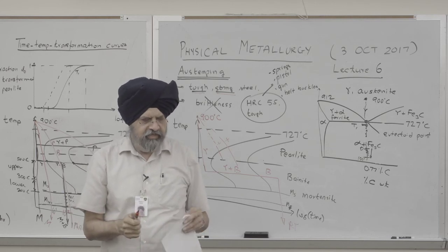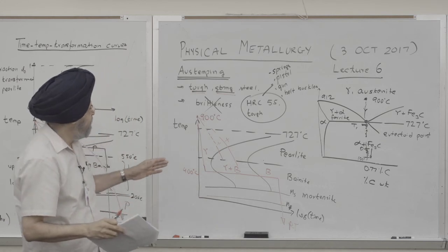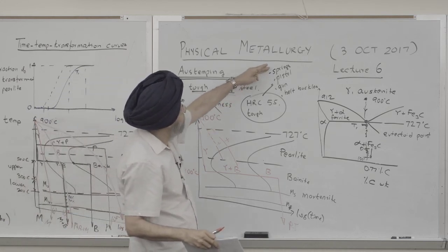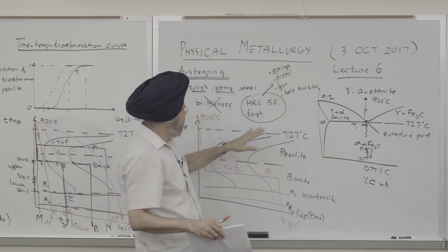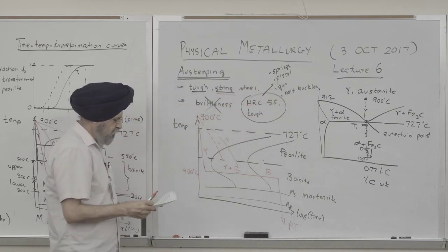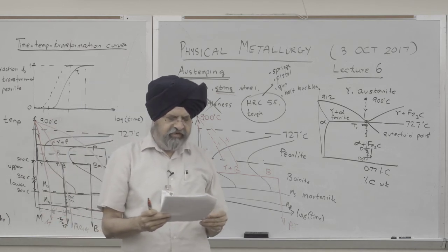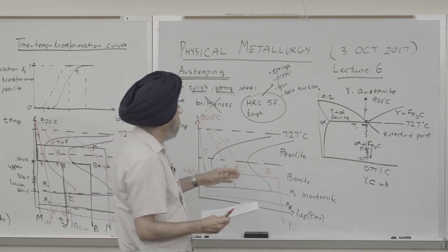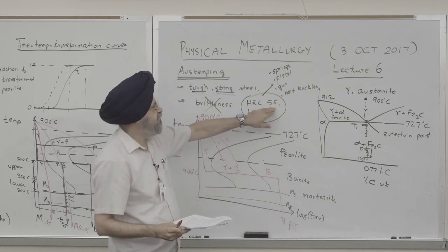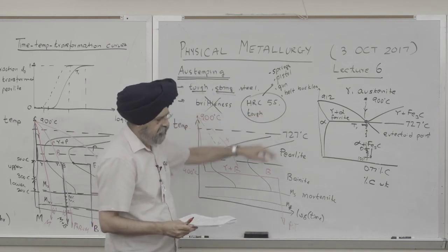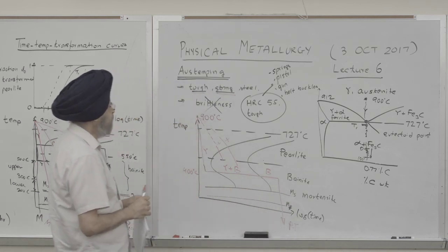So it cannot be too thick. So the steel has to be thin, and so springs can be thin, pistol parts, gun parts are thin, belt buckles are thin. So this technique of austempering is practical, and it gives you good hardness. You can get up to HRC 55, which is very hard. So that's one application of time temperature curves.